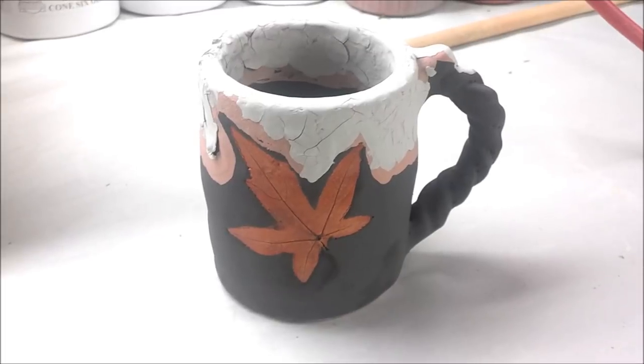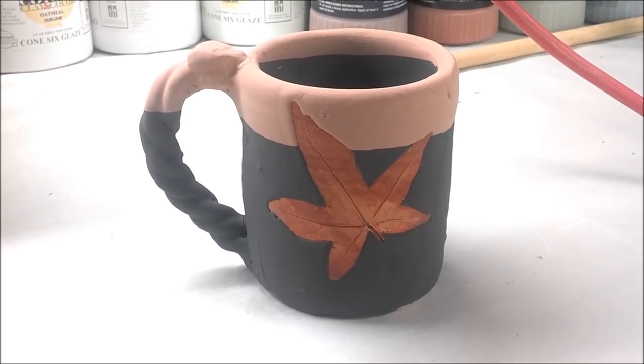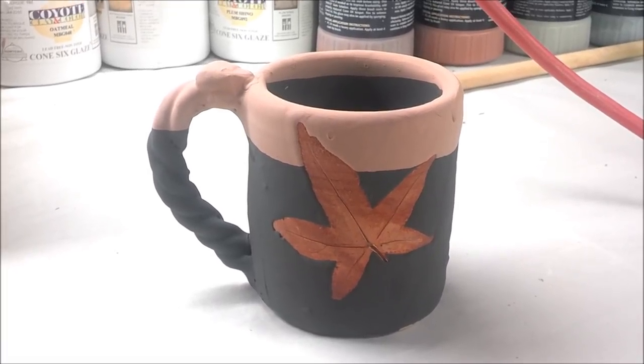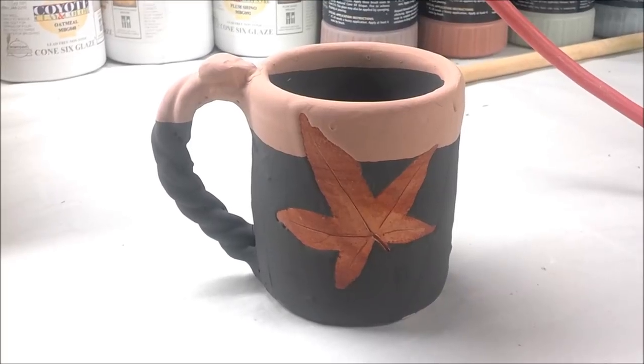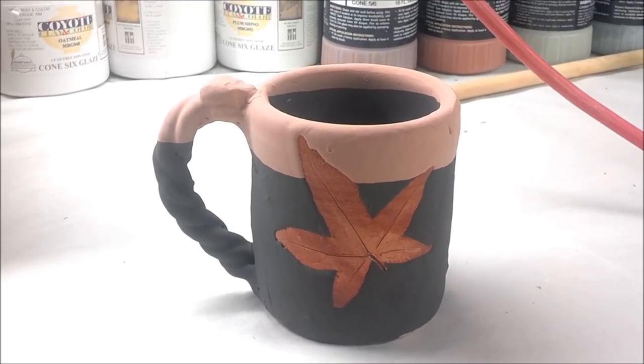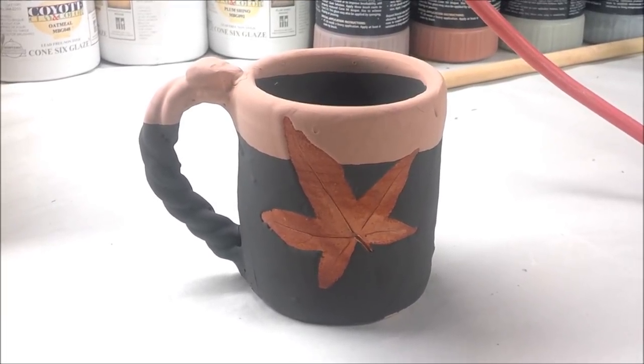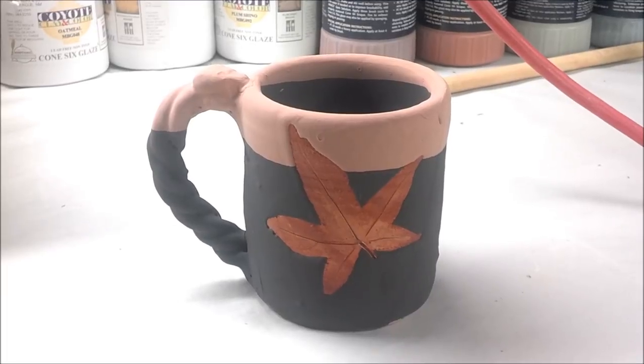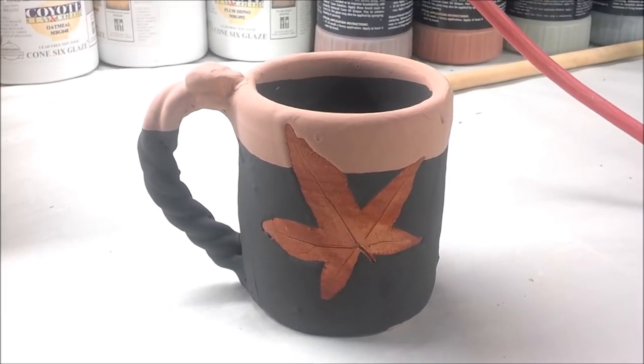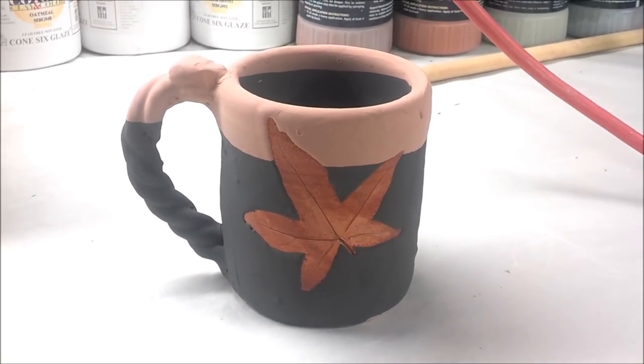On this mug I used Laguna Gloss Black on top with Red Gold. I tried this last time and the mug was a disaster — I think it was because I had forgotten to put glaze on the rim of a few mugs after the kiln was on at around 200 degrees. The wax disappeared and when it fired it kind of ran. So I'm not taking any chances this time and just put a little on the rim to see what happens.